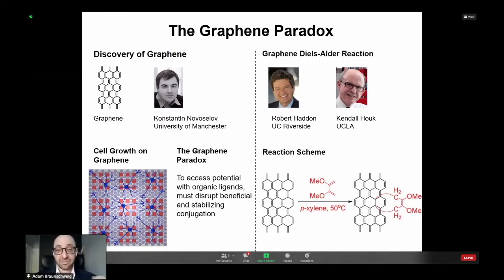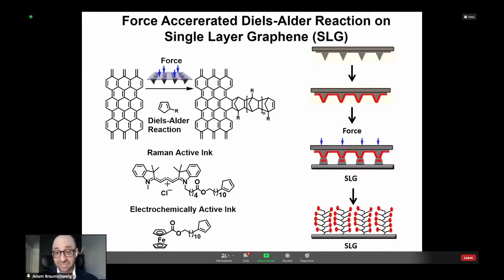And what we did was we found some older work from the Haddon and Houk group, where they looked at graphene flakes in solution, and they saw that these flakes could behave as dienes in a Diels-Alder reaction under some very specific conditions. At 50 degrees, it went forward, but at higher temperatures, it went backwards. And nevertheless, what they did was they proved that graphene flakes at least could act as dienes in the context of 4+2 Diels-Alder reactions. So we thought to ourselves, could we use the same idea, because Diels-Alder reactions are also pericyclic reactions with negative activation volumes. Therefore, this should work here as well.